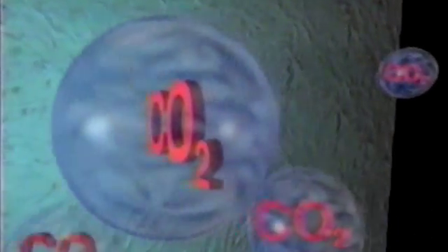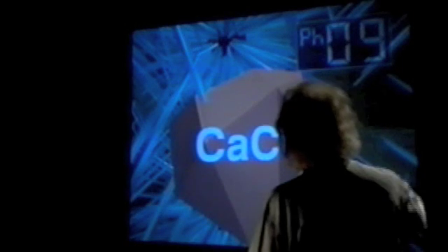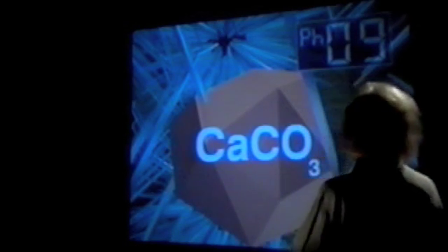In these conditions, the steel bar is covered with a stable and compact rust layer, which protects it from corrosion. This condition of passivity, however, is altered through the effect of carbonation. When the carbon dioxide present in the air penetrates into the concrete, it reacts with calcium hydroxide and neutralizes it. There is a lowering of the basicity of the environment. And with a pH below 11, the steel reinforcing bars inside the carbonated concrete are no longer protected.